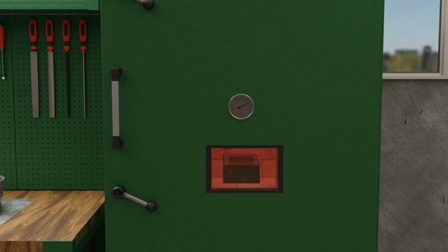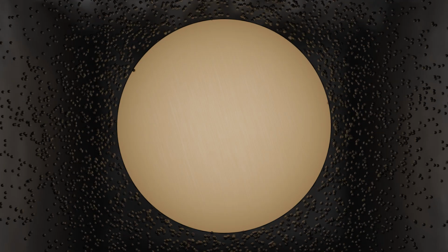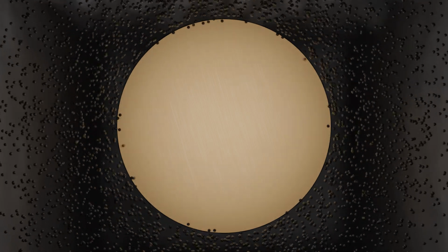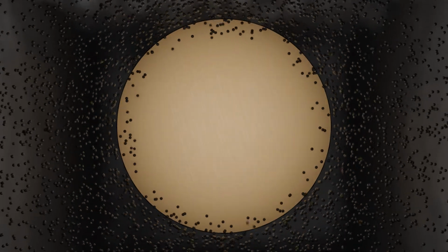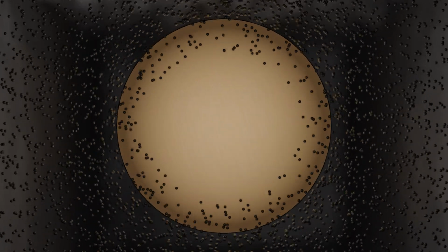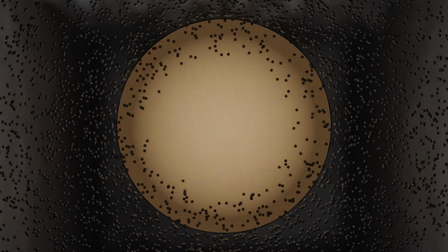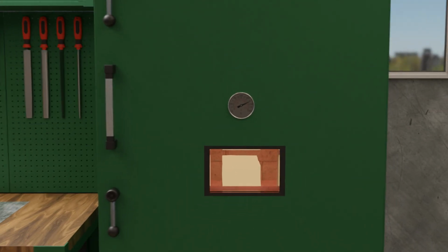As a result of the high temperatures, the carbon in the environment diffuses into the surface layer of the component and causes the carbon content there to increase to a hardenable level of around 0.8% carbon, while the core remains low in carbon. This accumulation of carbon in the surface layer is known as carburization. The depth of carburization is typically between 0.1 and 5 millimeters.